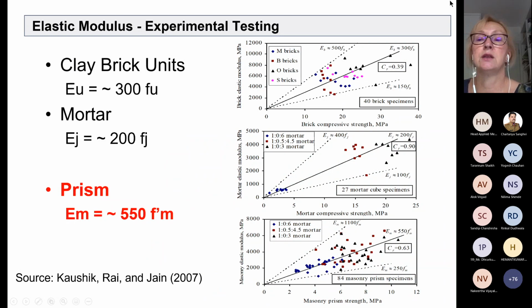The tests that were done by, again, the same group, Rai and Kaushik, Rai and Jain, showed that for Indian clay bricks, the average value was about 300 times the brick compressive strength, for the brick modulus of elasticity, which we are not interested in, but just in case. For mortar, it is 200 times the mortar compressive strength. But for the prism, please look at the red text, that is what we are interested in, it is about 550 F prime M.